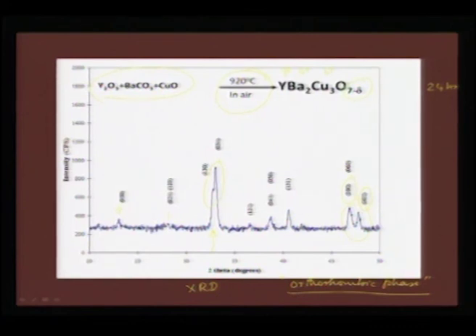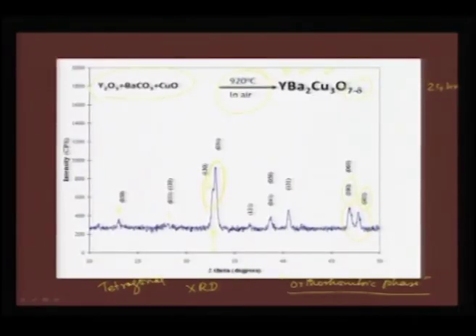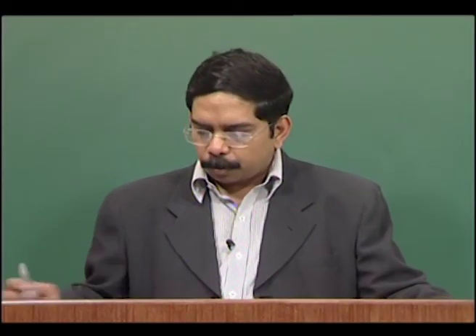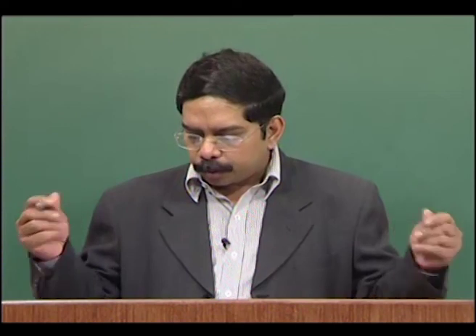If this peak is a single peak, then it resembles a tetragonal phase, and in that case even this major peak will not have this splitting. So, if there is no splitting, then it is a tetragonal phase, and if there is splitting, it is an orthorhombic phase. So, you can easily map whether you are working with a critical oxygen containing compound. If it is not the orthorhombic compound, you can be sure that it is not going to be superconducting. So, you can have fine tuning done just by looking at the X-ray mapping.